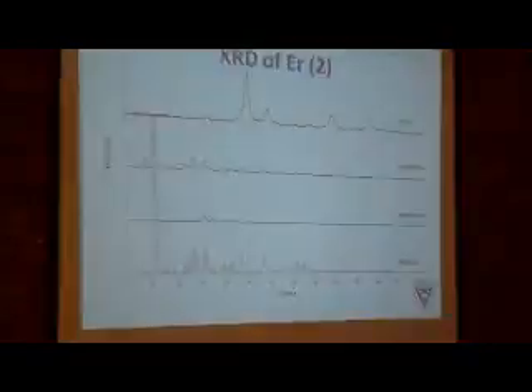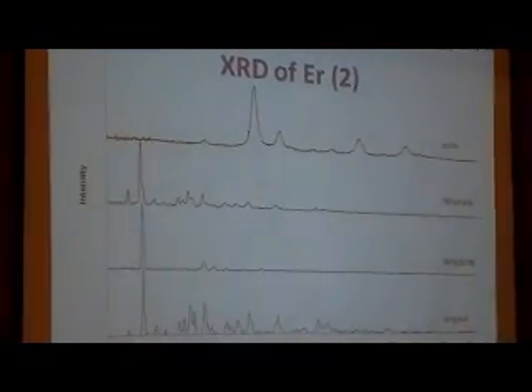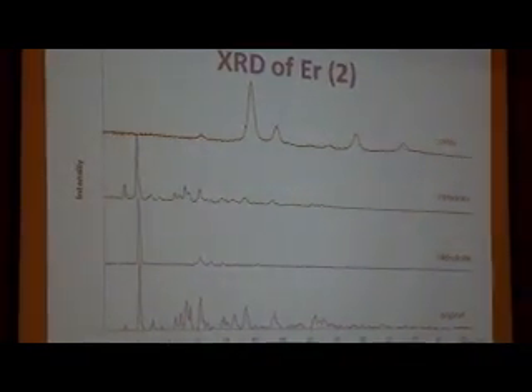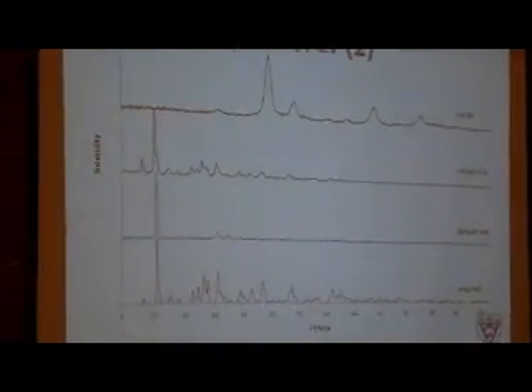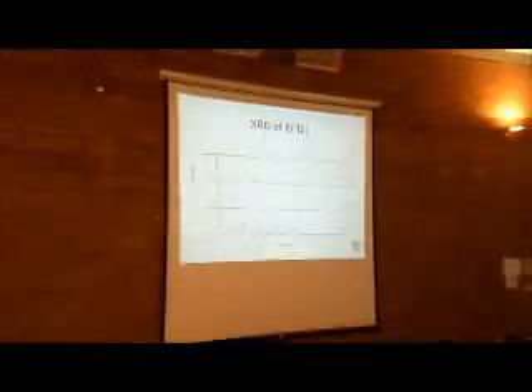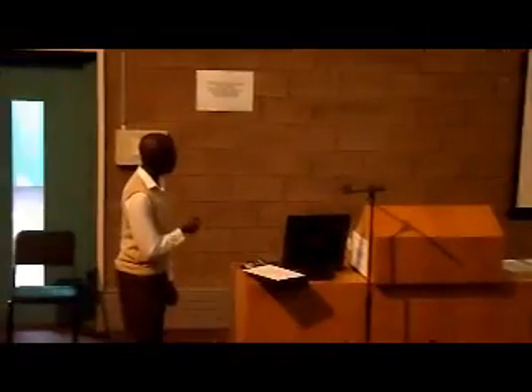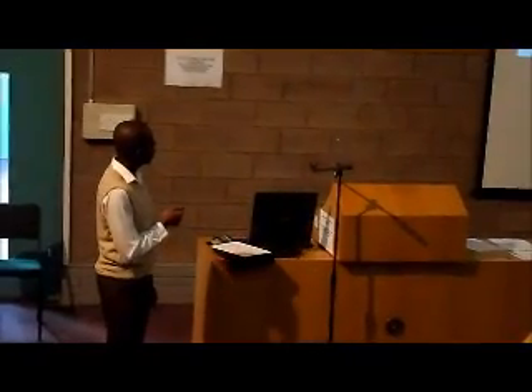Now looking at the XRD patterns, the X-ray diffractometry, we can see this is the original spectrum over here. It's quite messy, unfortunately. And due to the fact that it was so messy, we decided not to index the planes and find the crystallographic data. This would take too long, as we would need to have constructed a single crystal for single crystal XRD. Upon dehydration, you can see we have a huge loss of information over here. So this is probably due to the fact that most of the waters have been lost. And then upon rehydration, you see that we partially reobtain some of the data seen in the original.